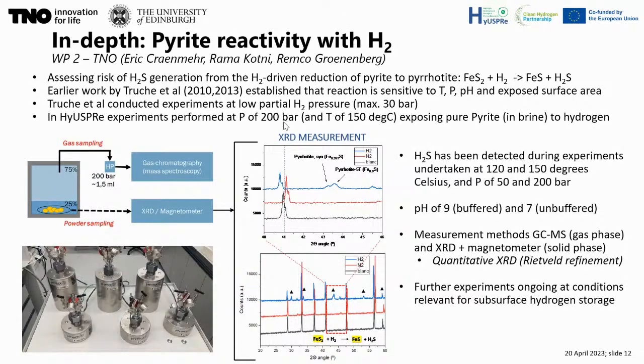So then a more in-depth study into the pyrite reactivity with hydrogen and what that would mean for the risk of hydrogen sulfide generation from the hydrogen-driven reduction of pyrite to pyrrhotite. Also building on earlier work by Truche et al., who established that the reaction is sensitive to temperature, pressure, and pH, and also the exposed surface area of the mineral pyrite. Truche conducted these experiments at low partial pressures of hydrogen, to a maximum of 30 bar, and the HyUSPRe experiments are performed at a pressure of up to 200 bar and a temperature of 150 degrees Celsius, exposing pure pyrite in brine to hydrogen.